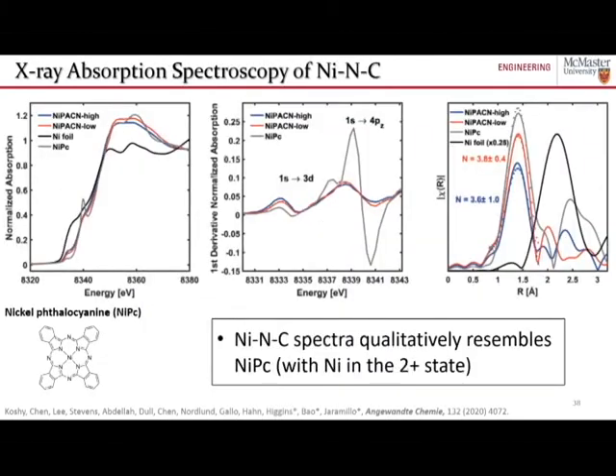Now, we did some X-ray absorption spectroscopy of these materials, and particularly the key thing that I want to highlight is we compared the XAFS spectra of our materials with that of a metallic nickel foil and a nickel phthalocyanine molecule with the structure shown at the bottom left there. And ultimately what we found is that the nickel nitrogen carbon spectra qualitatively resembled the nickel phthalocyanine with the nickel in the 2+ state.